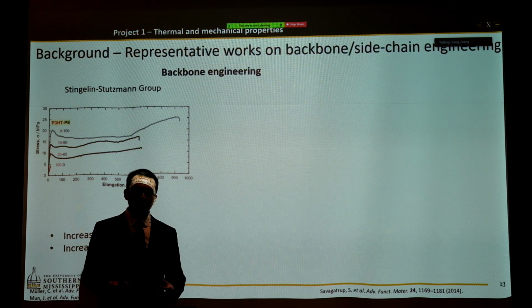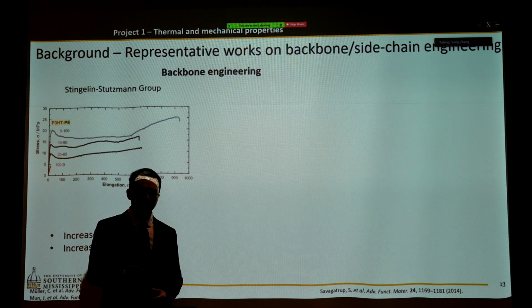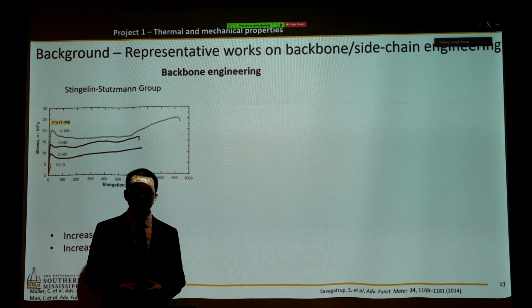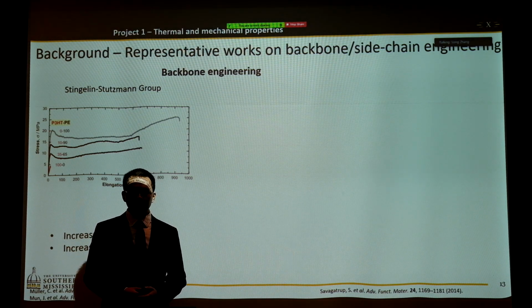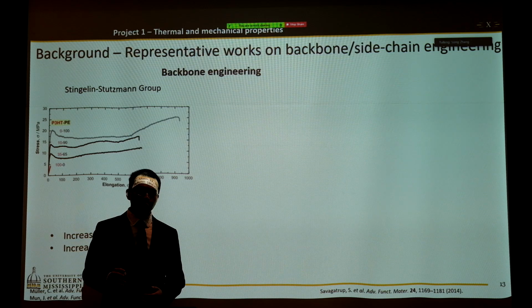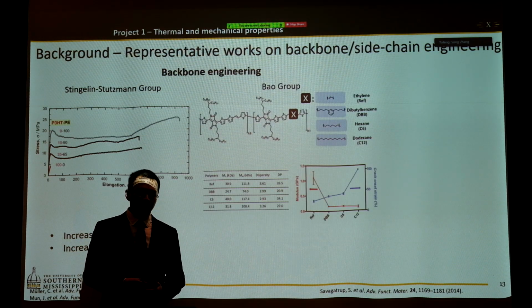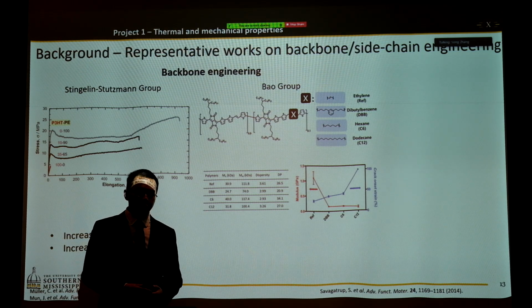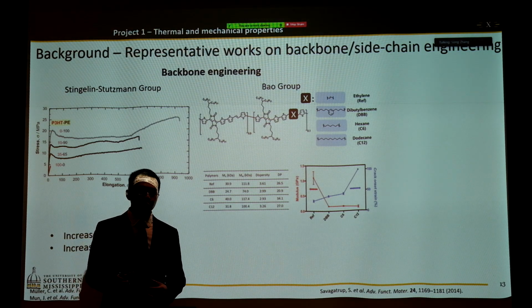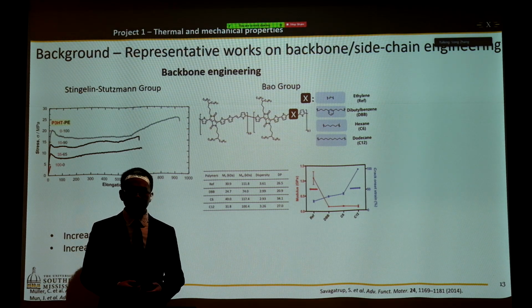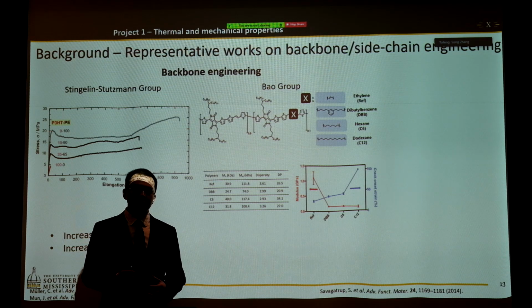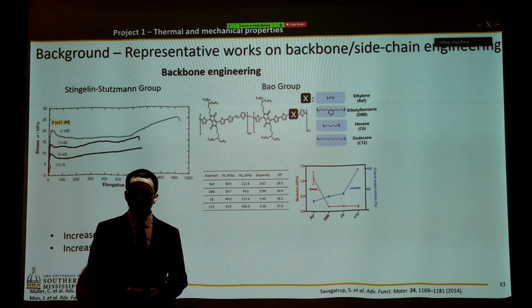So they found that with incorporation of more polyethylene in the backbone, the elastic modulus increases, and the crack onset strain increases as well. However, the increased elastic modulus might not be what we want for flexible electronics. Dr. Bao's group introduced a different technique. So they introduced conjugation breaker spacers, for example, in this case, C6 and C12. It can sufficiently decrease the backbone rigidity, and the modulus is dropped, and crack onset strain is increased.